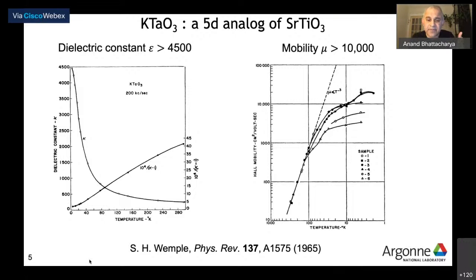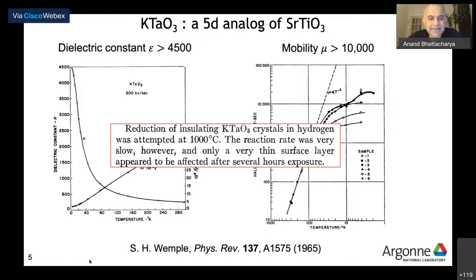And if you do manage to dope this, and this was done way back when, in the 1960s, actually, about the same time that STO was being studied, at Bell Labs, what they showed was that if you chose the right conditions and grew your sample such that it was doped, you would get electrons and mobilities that are quite high, like 10,000 in the bulk, right? But there's a line in that 1965 paper, if you go read it, it says, reduction of insulating KTO in hydrogen was attempted at 1,000 degrees centigrade, okay? The reaction rate was very slow, however, and only a very thin surface layer appeared to be affected after several hours of exposure. A little different from STO, okay?